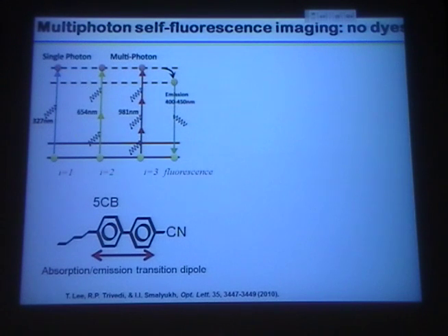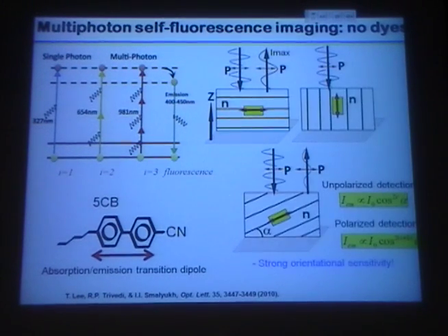And so in all of those cases, regardless whether you use 1-photon, 2-photon, or 3-photon absorption process, we would always get emission in roughly the same range, from 400 to 450 nanometers. Now, doing the excitation in the visible or near infrared part of the spectrum is much easier than in UV, especially in near infrared, because this will not also interfere with the detection of the fluorescence light, right? So it will make our life easier.